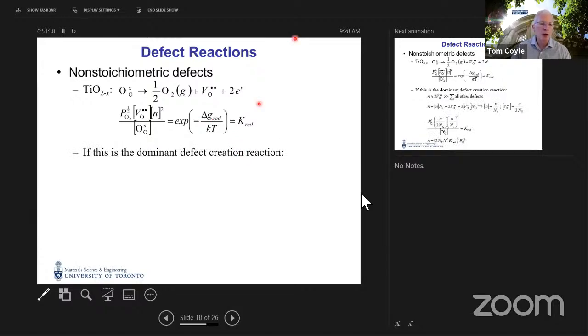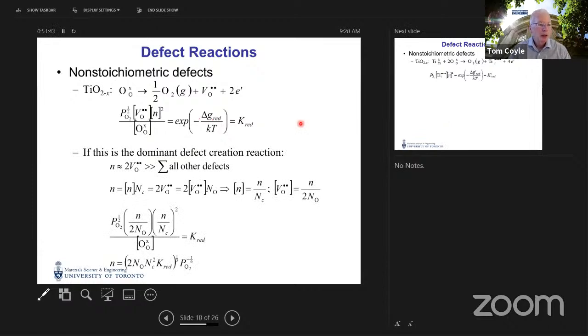Again, under the assumption that no other defect creation reactions are significant, we have the number of electrons in the conduction band is equal to twice the number of oxygen vacancies created. And again, working with the definition of the various terms, we can substitute for the mole fraction of oxygen vacancies in terms of the fraction of electrons in the conduction band. And since we're interested in conduction, we're interested in the number of electrons in the conduction band, which can be related again to a constant multiplied by the oxygen partial pressure to the minus 1/6 power.